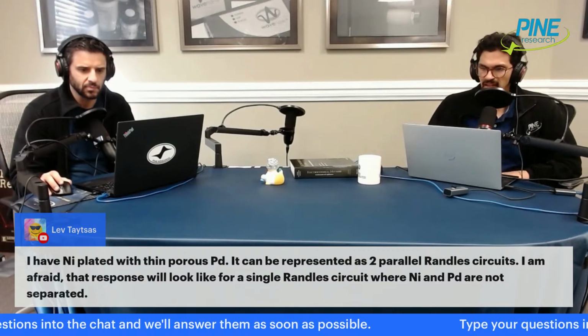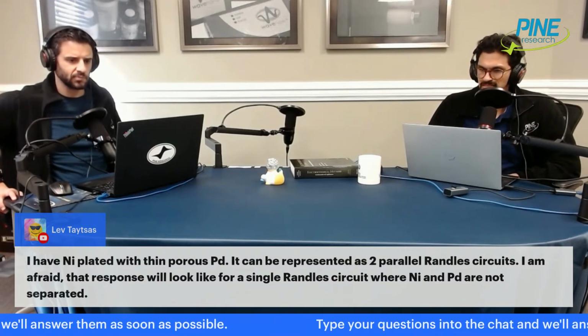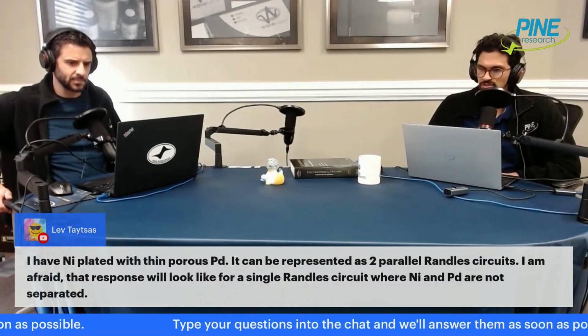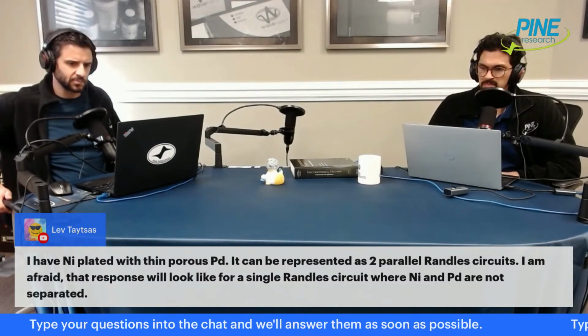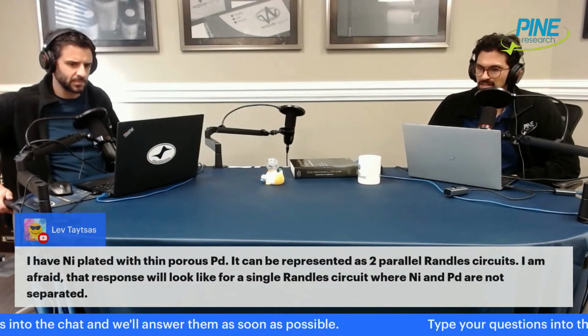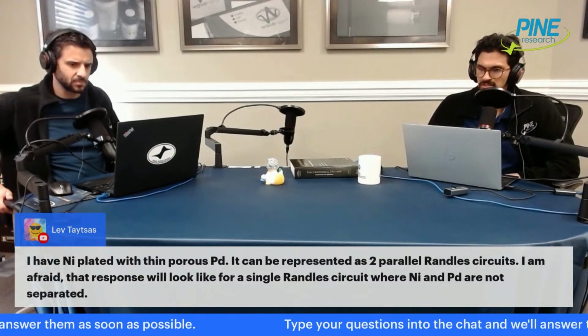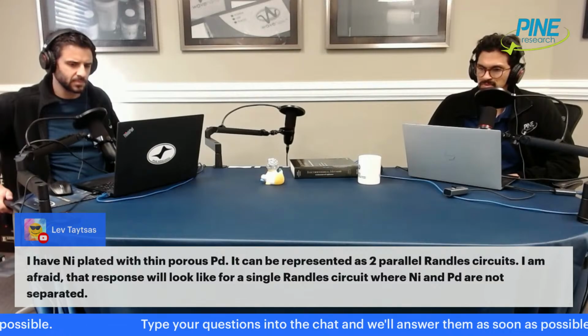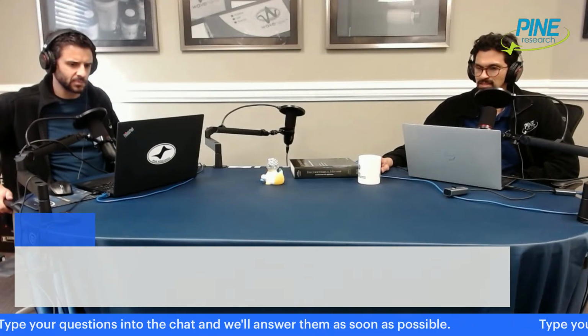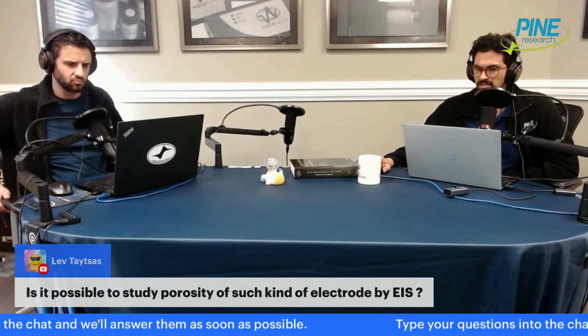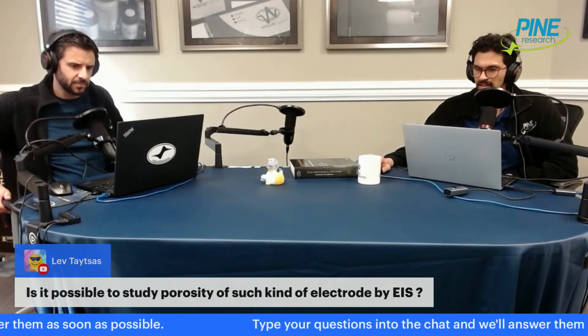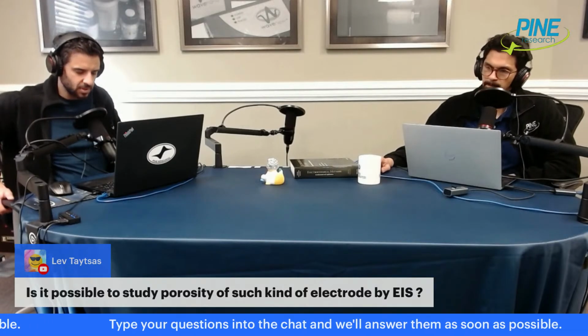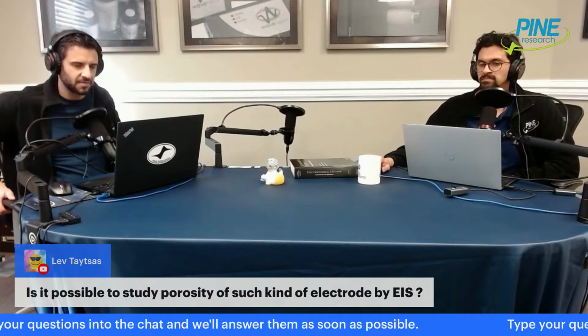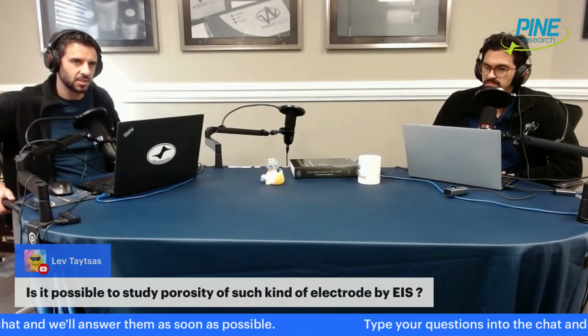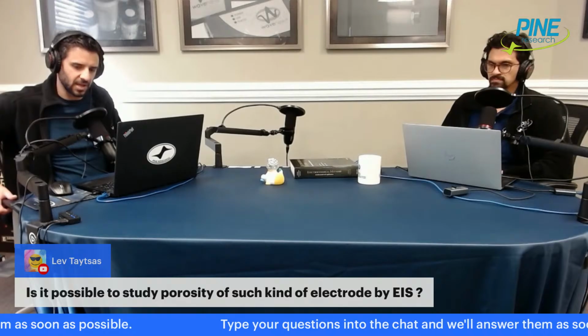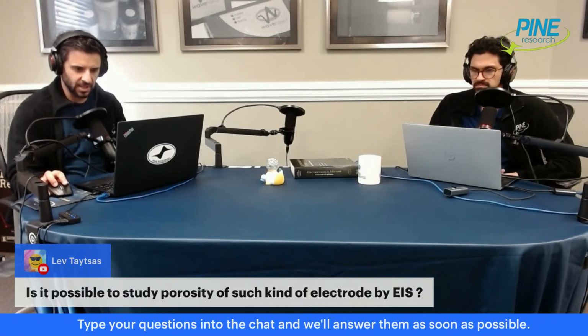Lev asks, I have nickel plated on thin porous palladium. It can be represented as two parallel Randles circuits. I'm afraid the response will look like a single Randles circuit where nickel and palladium are not separated. Is it possible to study porosity of such an electrode by EIS? Yeah, so you would want to do something like a transmission line fit. Transmission lines are typically used for the calculation of porous electrodes.